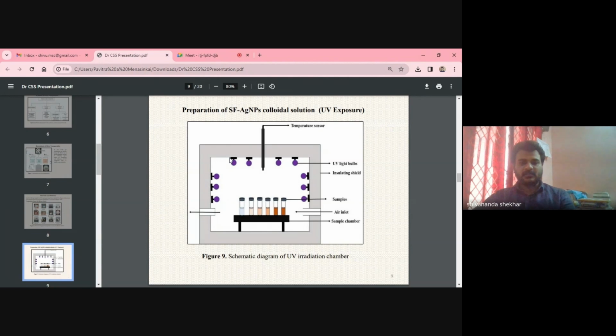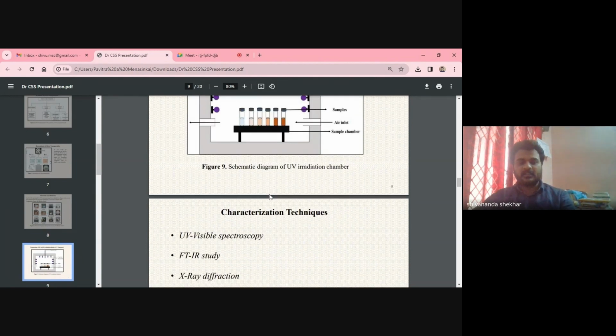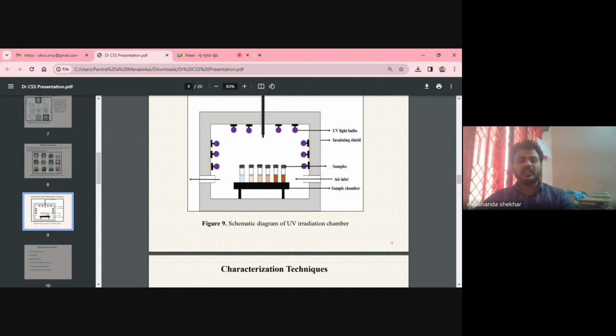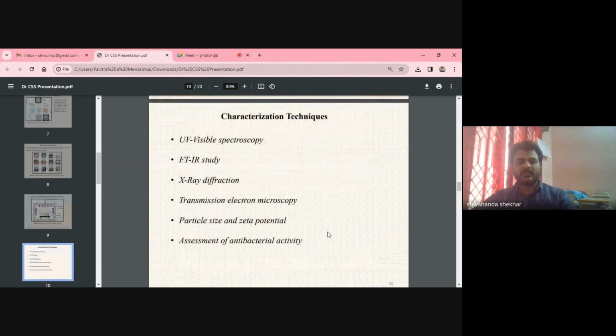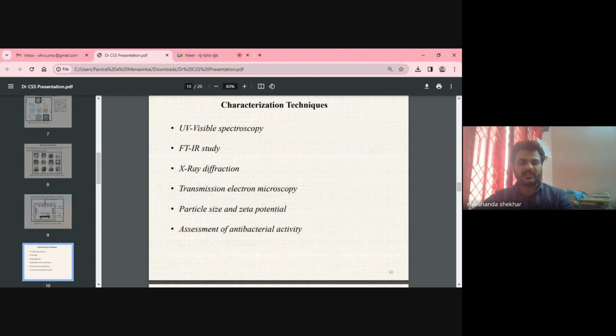This is the schematic representation of the synthesis of silver nanoparticles in silk fibroin solution. Later we get the colloidal silk fibroin silver nanoparticle solution. The composite solutions we further characterized with different techniques: UV visible spectra, FTIR, XRD, transmission electron microscopy, particle size, and assessment of antibacterial activity. The UV, XRD, TEM, and particle size are all size determination characterization techniques. So we did all these characterization techniques.